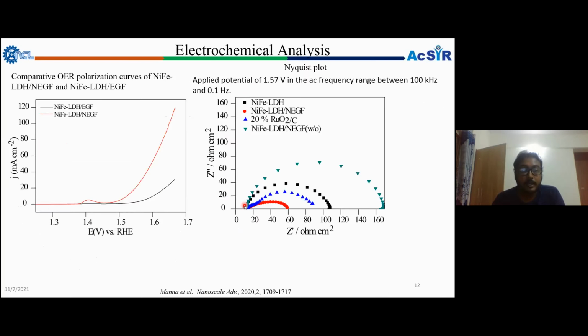To further know the importance of the nitrogen doping over the graphene, we have compared the LSV plot without nitrogen and in presence of nitrogen. There is a huge change in the activity. Similarly, we have done the impedance measurement. Here you can see the impedance for our catalyst is showing lower charge transfer resistance, which is why it has better activity.